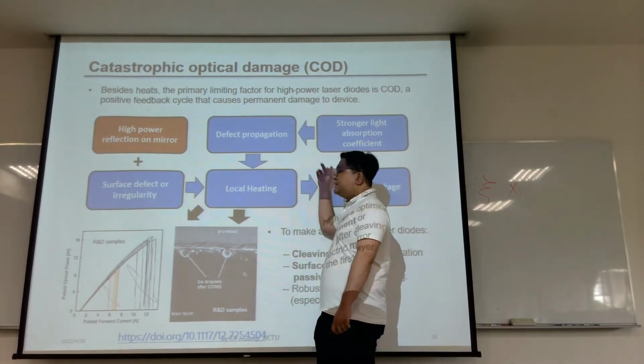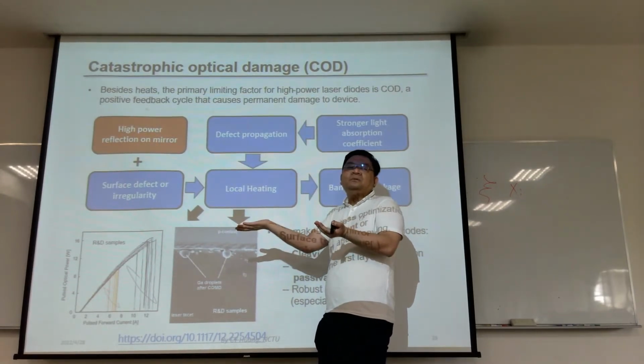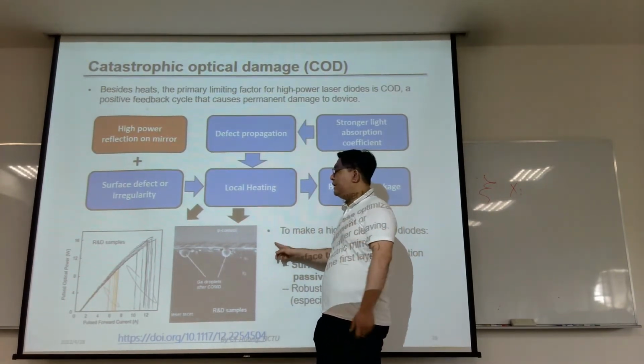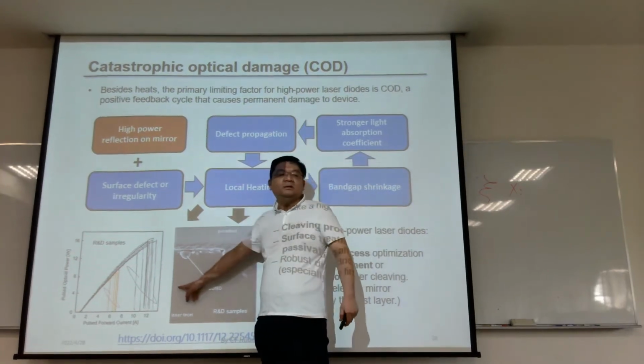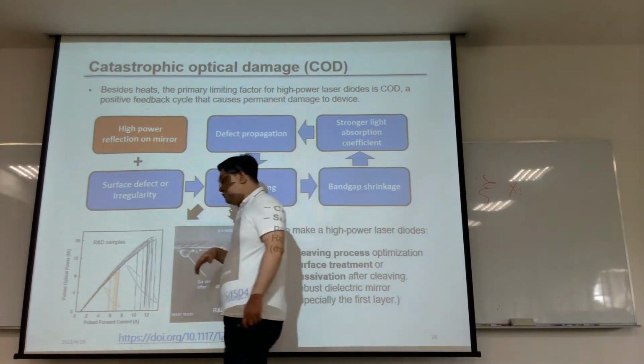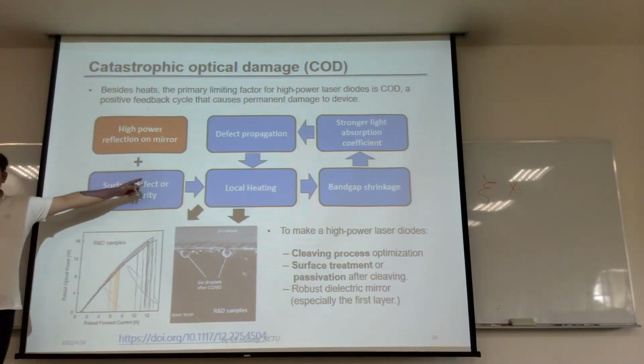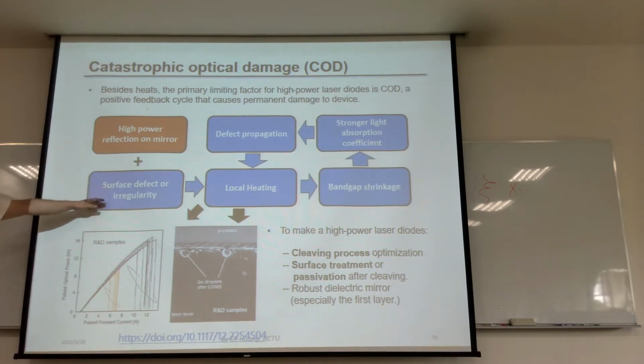But after such a cycle, oxide deposits on it, and then you don't have such a high mirror anymore. Then your laser doesn't lase anymore. So this kind of failure is irreversible. Once it happens, your device is dead because your good mirror doesn't exist anymore.